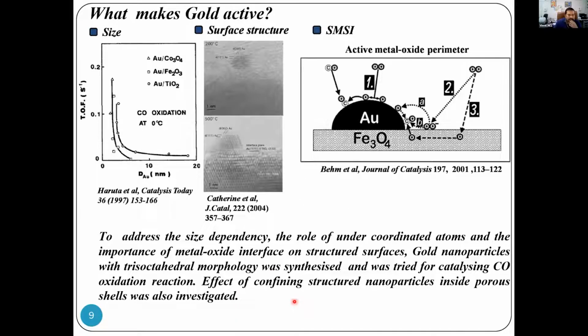So why does gold become active? There are several reasons for that. One of the reasons that has been proposed by Haruta and also by Wayne Goodman is the strong size dependence. What happens is, when the size becomes less than 10 nanometers, there is an exponential increase in the catalytic activity.